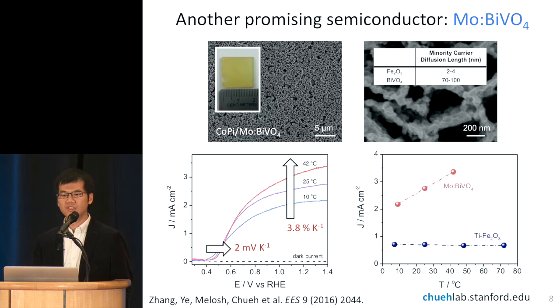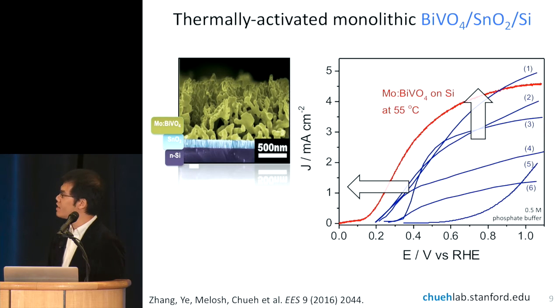So here we're really seeing a very dramatic enhancement by temperature simply by having more of the light being absorbed in the minority carrier diffusion length rather than in the space charge region. So we took advantage of this and we created a bismuth vanadate cell that is coupled with a silicon tin oxide junction. So this is essentially embedding a photovoltaic into the system.